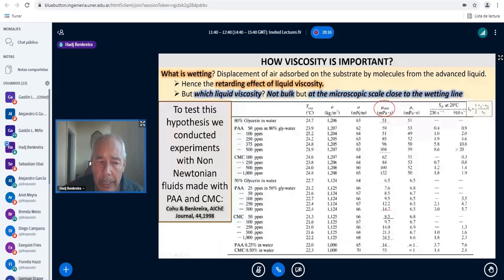And it's the same when you're looking at CMC. If you increase it to 100 ppm, 250, 500, 1,000, you can have apparent viscosities of 62, 84, 100, 132, but the solvent viscosity still stays the same. It's still glycerin and water. And so on for all the other fluids that we are showing in here. So when we looked at the air entrainment velocity, we saw no difference. We saw that what really mattered was the base fluid that was controlling the air entrainment velocity.